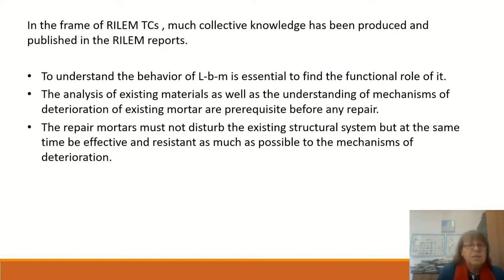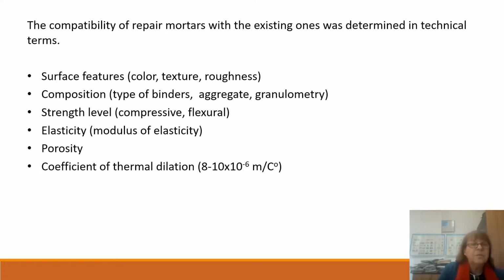Many messages emerged, such as that before any repair, a prerequisite is to understand the functional role of the mortar and also the mechanism of its deterioration. The priority of any repair mortar is not to disturb the existing structural system, and at the same time to be as effective and resistant as possible to the mechanism of deterioration. It was great progress in designing repair mortars to define compatibility in technical terms. We found that the most influential parameters were surface features, composition, strength level, elasticity, porosity, and coefficient of thermal dilation.